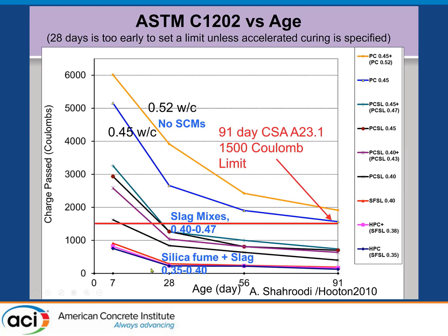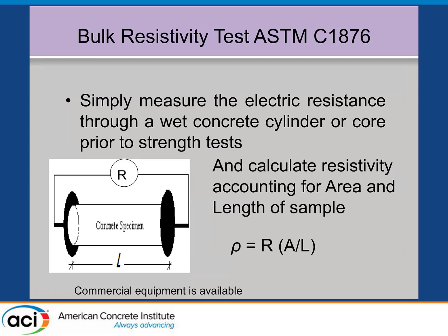If you use silica fume and slag, you can meet it at 7 days. The silica fume reacts so quickly. But we don't want to make that our only option. So the C1876, which was just recently standardized, is a fairly simple concept. You take a saturated concrete again, you calculate the resistivity, which is the resistance to electric flow, normalized for the area of the sample and the length of the sample.